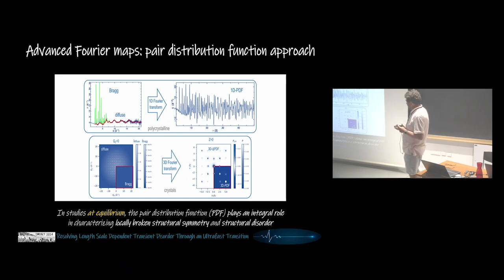And in that, you do have actually a conventional diffraction pattern that extends, which is important, to very high Q, which actually determines the resolution in real space. And you also have a diffuse scattering channel, and so you can treat those two signals simultaneously on equal footing. And so you end up with basically a function in direct space, which has intensities that correspond to interatomic distances. And you can interrogate your signal over different length scales to determine actually how local and the average structure connect.